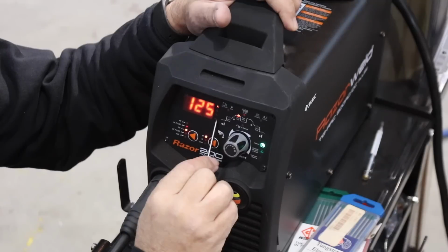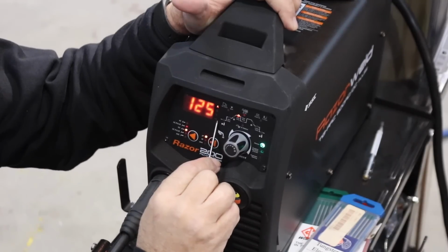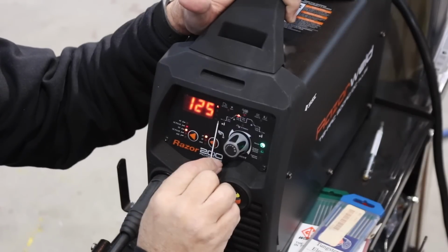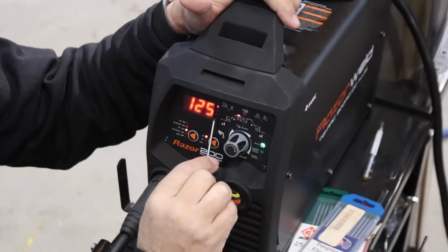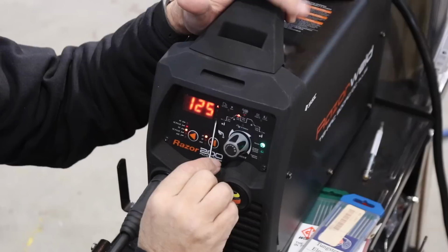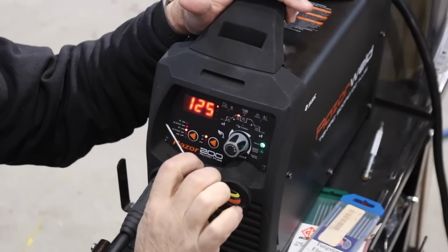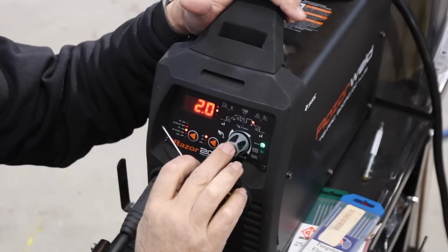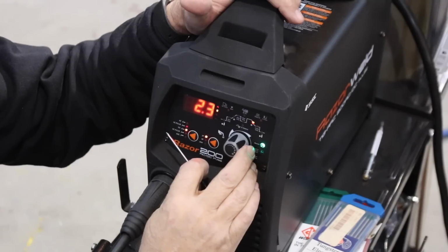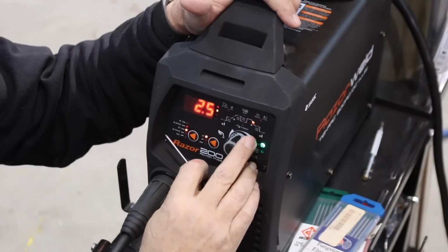Your choices are either to shut off all at once, and then you're probably going to leave a little crater dot, which is a defect, or you can taper off the amperage, avoid blowing the end away, avoid a crater dot and have a nice ending to the weld. You just have to play with that. It's different for different thicknesses, but with a torch switch I'd probably want maybe